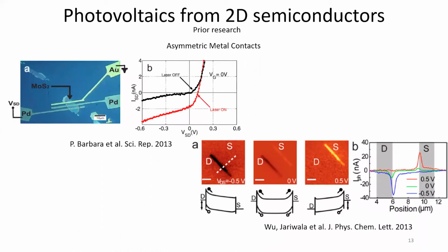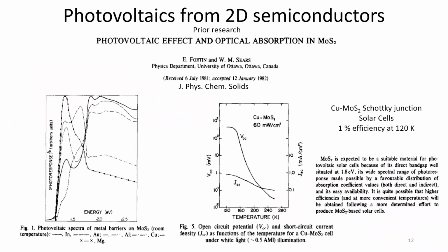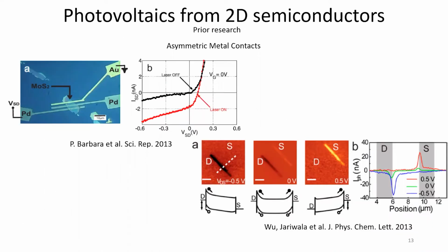And these are some of the earliest reports over here, where Paul Barbara back in 2013 demonstrated, again with a very similar concept, just Schottky junction, but now we have asymmetric Schottky junctions, or in other words, one ohmic and one Schottky contact. And so you can use these asymmetric metals such as gold and palladium, shine light on it, and you do end up seeing some photovoltaic effect. So there you go. They can be used as photovoltaic semiconductors.